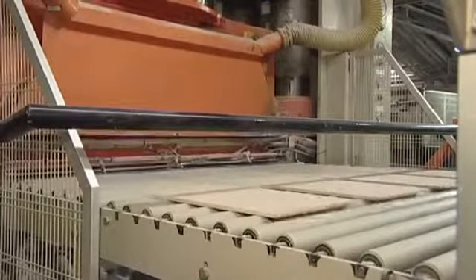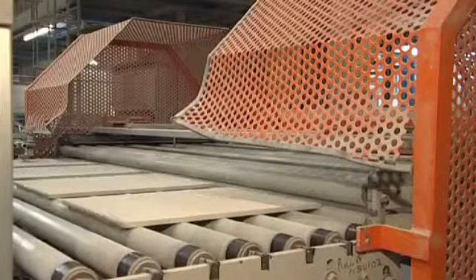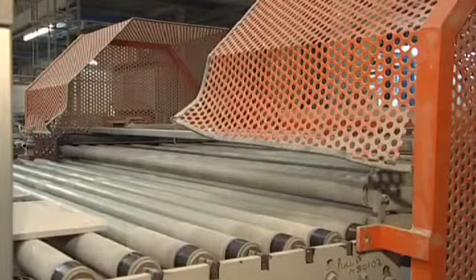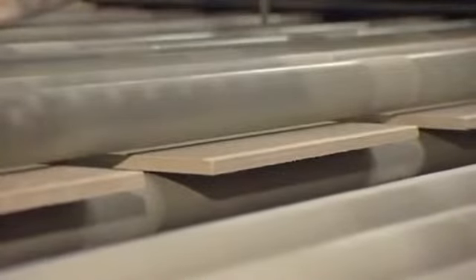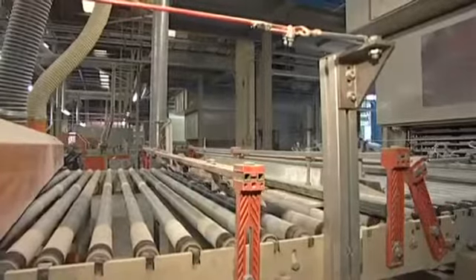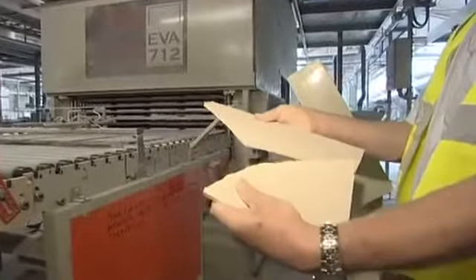The granulate is used in the tile presses, which are hydraulically operated and form tiles at a rate of up to 240 per minute for the 100 by 100 millimeter sized tiles. The tiles are pressed at a pressure of up to 150 tons and dried to a moisture content of around 0.5% and surface temperature of about 80 degrees centigrade. Whilst the tiles are not fired at this stage, they are strong enough to be fed along conveyors for decoration.